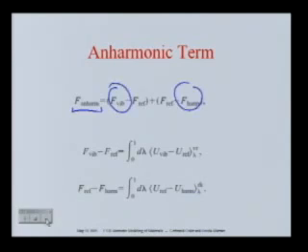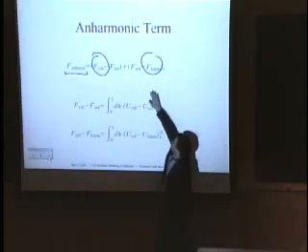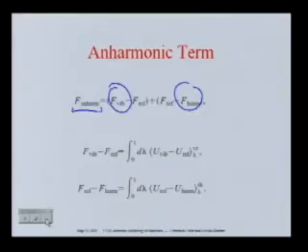And the trick consists in introducing a reference classical potential, so that a lot of your expensive sampling of the phase space can be done with classical simulations, and the very expensive ab initio simulations are only used to figure out what is the difference in thermodynamical terms between your quantum potential and your classical potential. So again, just a mathematical term.